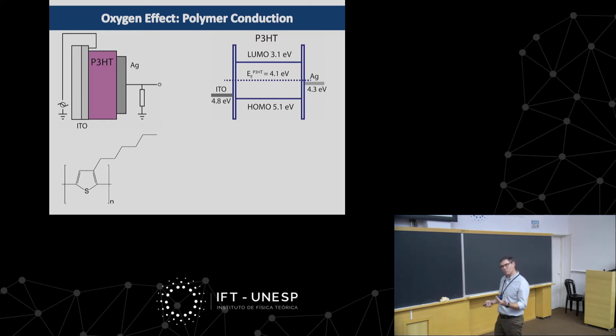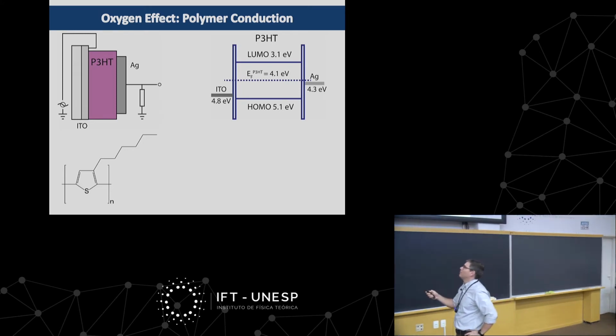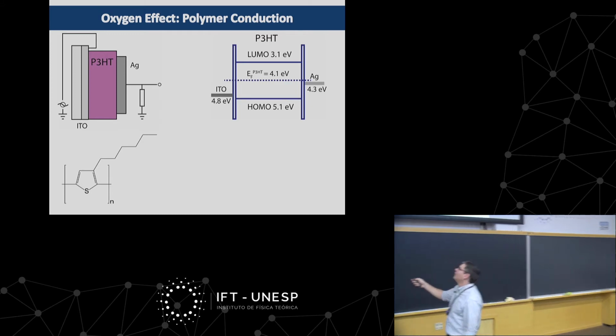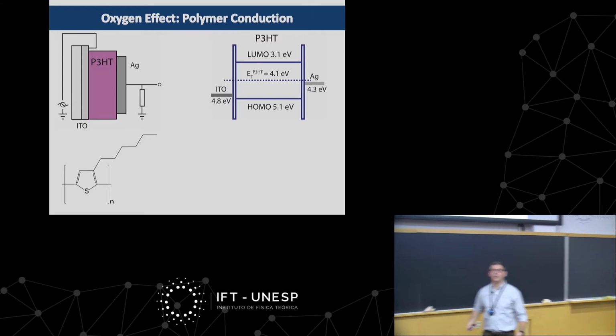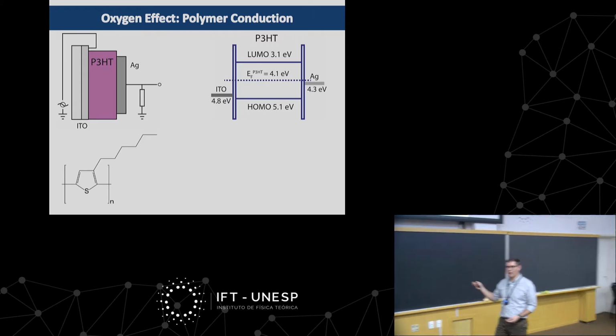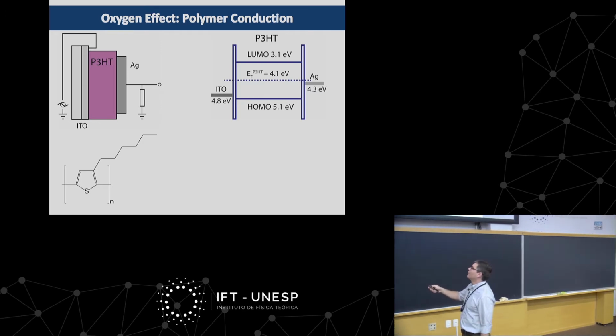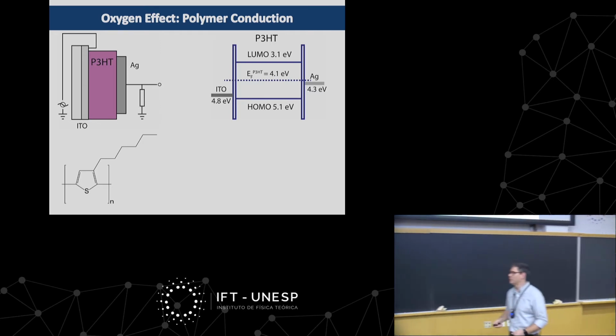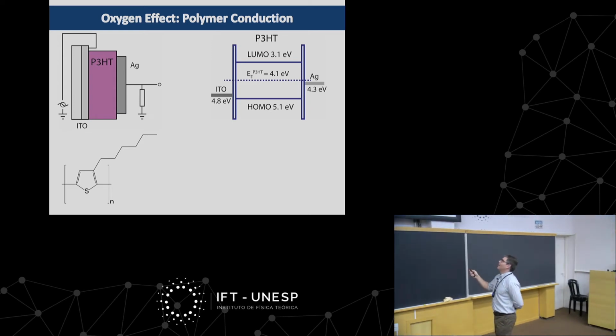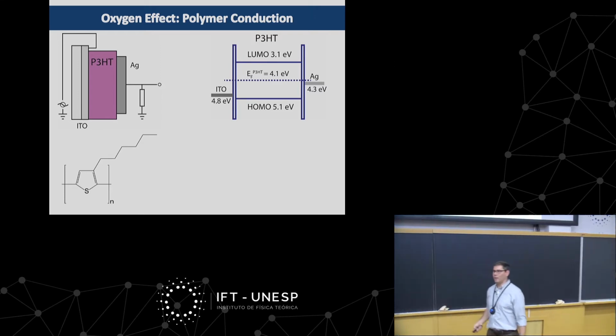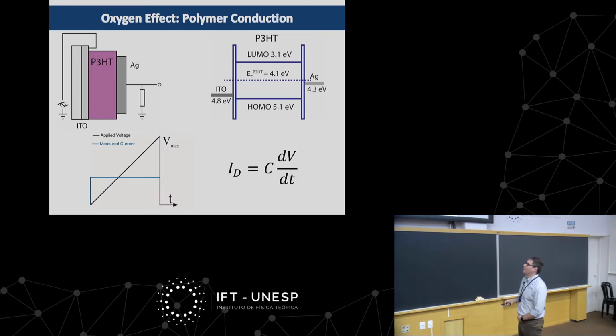So we wanted to look into more details of that process. What we did, we basically built in our lab a simple, what we call diode, which is a glass substrate and transparent oxide, the polymer film, and here a metal electrode, which is in this case silver. Okay, so we hook them together, so you can apply a potential. And here's the band diagram, where the HOMO and LUMO are basically the valence band and the conduction band of the material. And those numbers here are the work functions of ITO and the silver electrode.